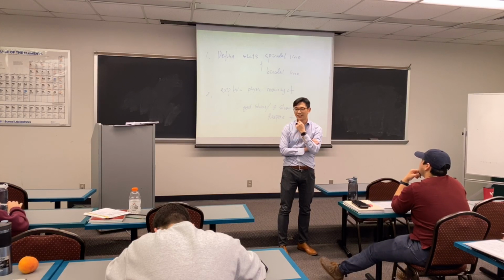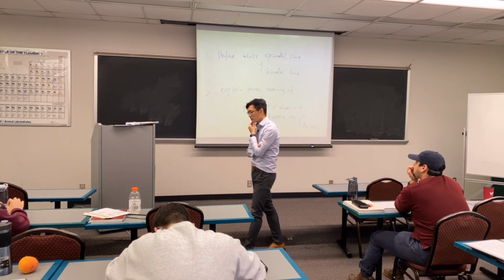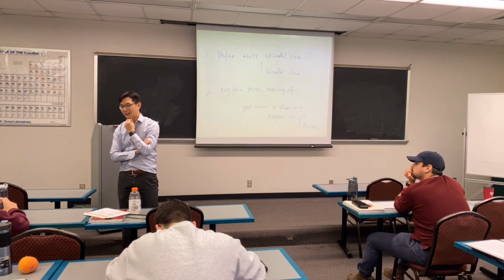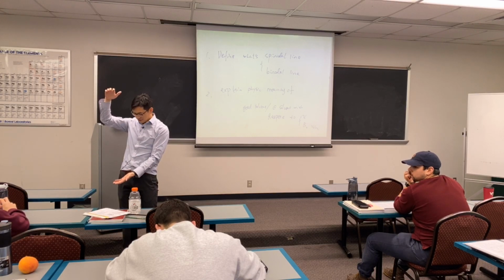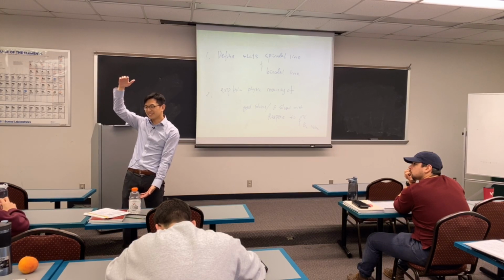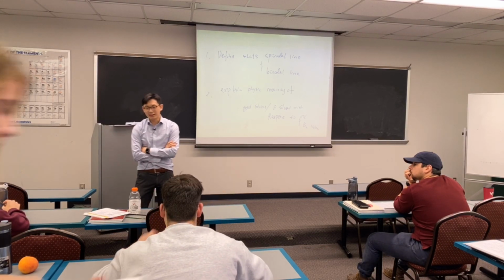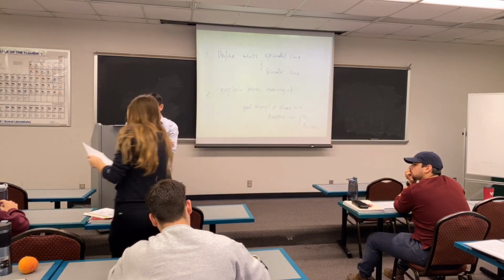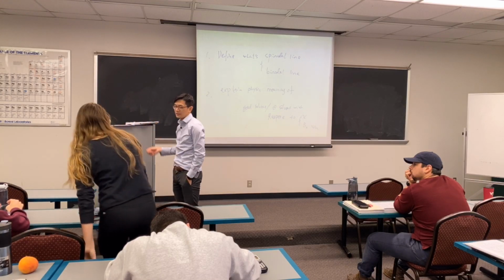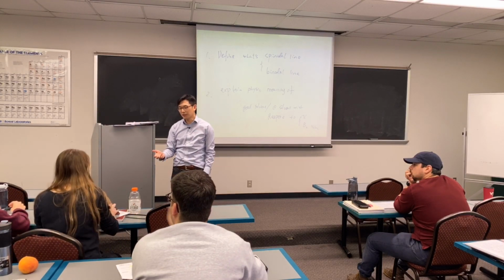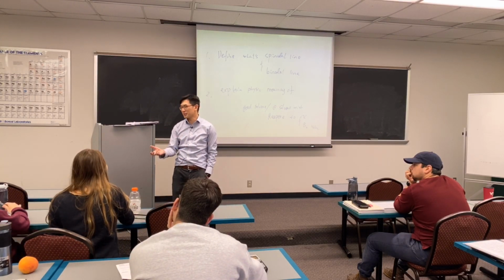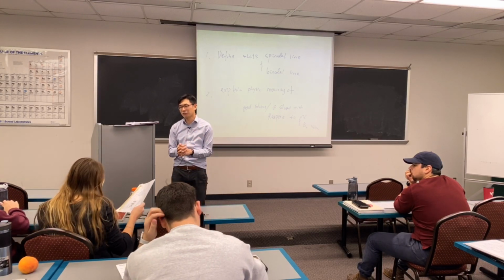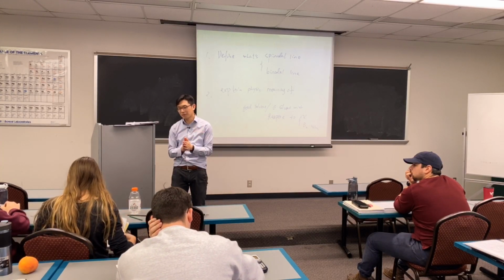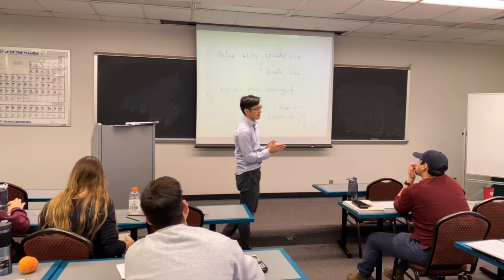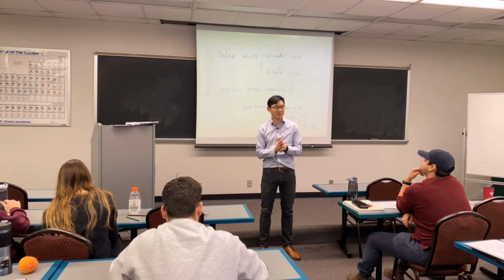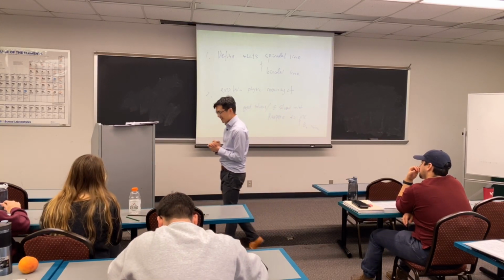I can give you an example that in very cold winter in the northern part of the U.S., you would have water become ice, start dripping down. You get these long ice chunks. They're not going to fall down before you give the system enough energy. So same argument for the phase separation. You need to have the system to have enough mobility to make it happen, okay? Mobility, I mean, you cannot freeze the polymer chain when you mix them. That's something called the kinetic trapped states, and it's quite common in some of the materials. Like Sergey will teach you guys about glass transition temperature, which I won't steal his thunder. He will teach you all about the science related to the glass transition phenomenon.